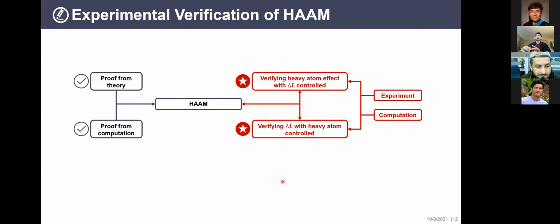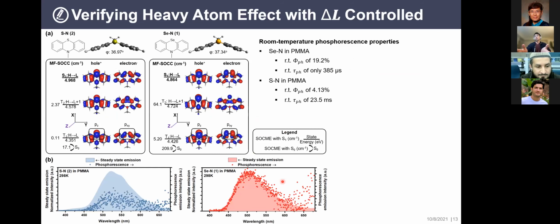So later on, we designed a series of experiments to verify this so-called HAAM concept through experiments and through computation. The first thing we did was think about whether we can fix the orbital angular momentum change while altering the heavy atom. So we chose the same molecular scaffold and replaced the selenium with sulfur, which is one row up in the periodic table of elements. We found that its overall performance is much lower and the lifetime is much longer, about two orders of magnitude longer. So this is very expected.